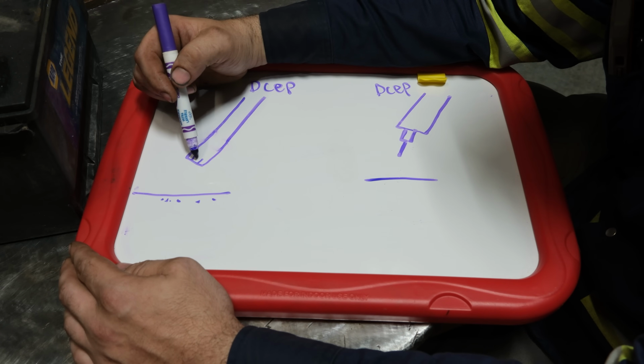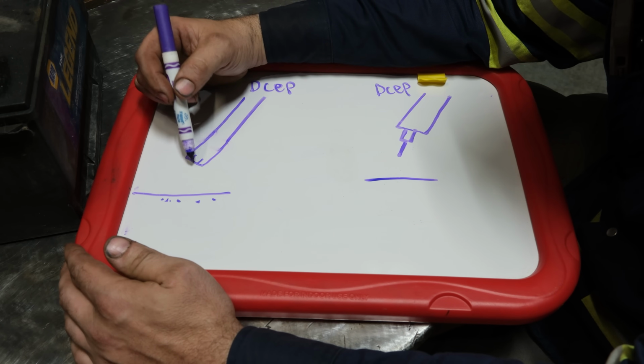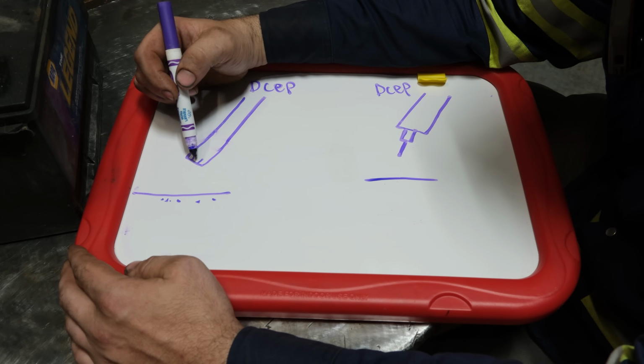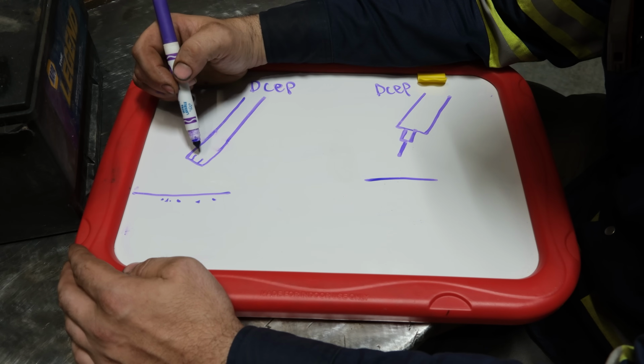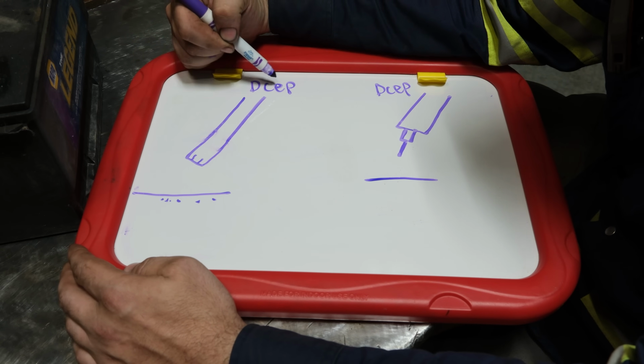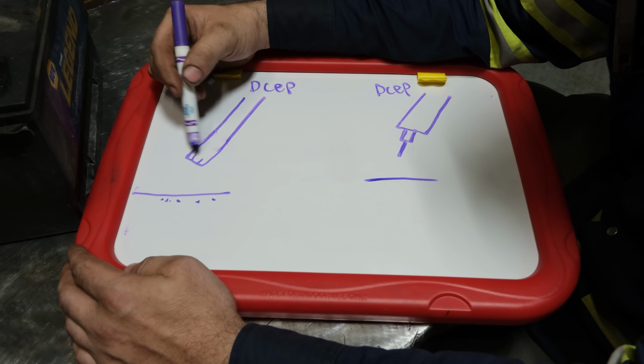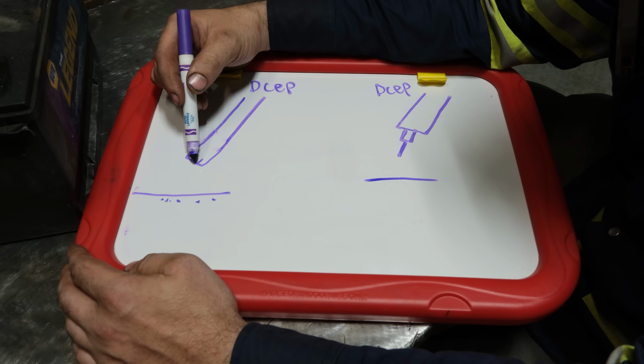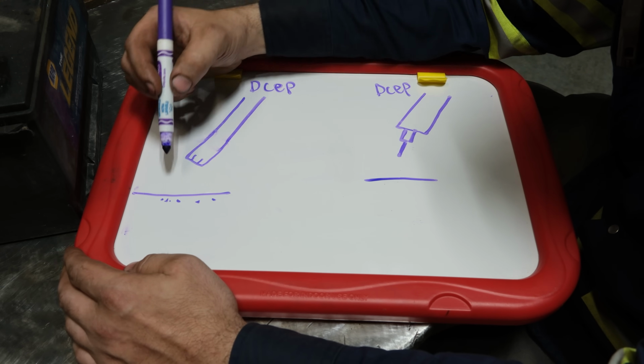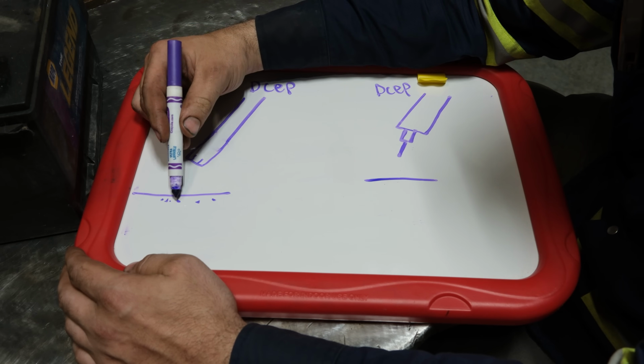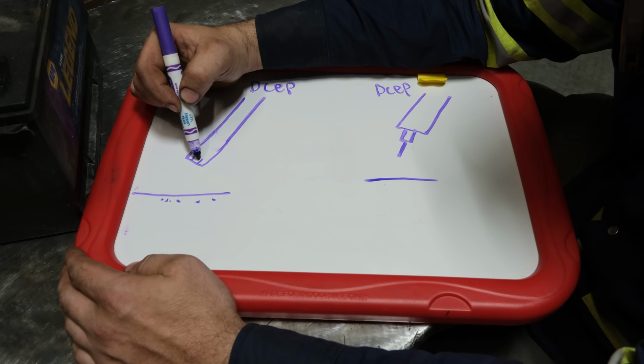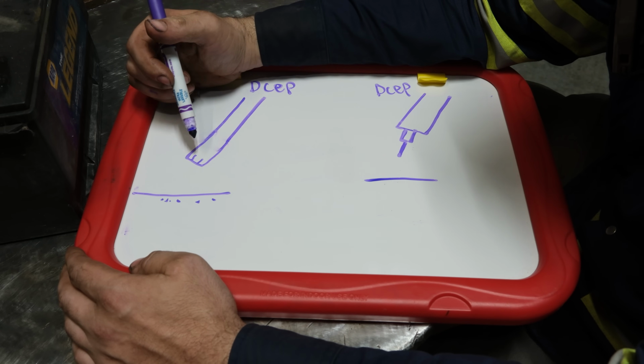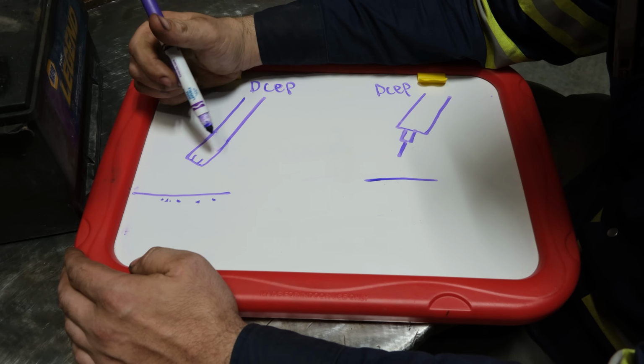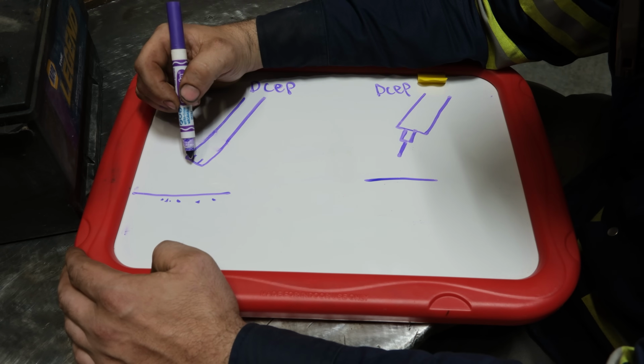So the hotter that you can get that rod tip, the better, because you get bigger balls and more droplets of molten metal, which is good. But if it was cool, like if you ran DCEN with stick welding, the tip of the rod will be cold, and you'll be more prone to more or less just having an arc across and not molten metal melting off of the rod tip. So in a lot of effects, you have to run EP to get stick to weld properly.